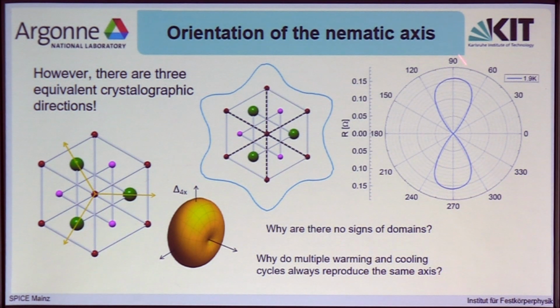And of course, you would also expect it to form domains. So instead of measuring in resistivity samples this very nice twofold symmetric shape, why don't we see something that looks more like this, which would be an average over multiple domains with the gap structure pointing along three different directions for each domain? Now, that is the one thing.